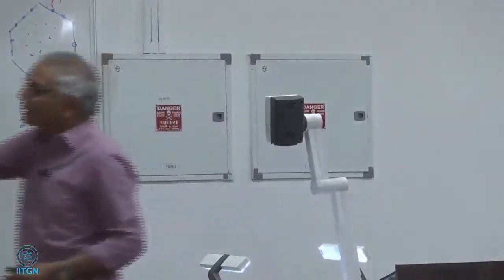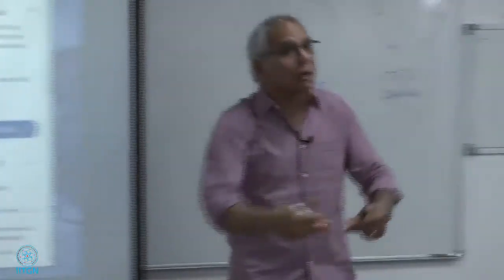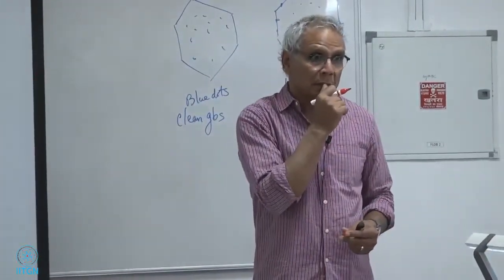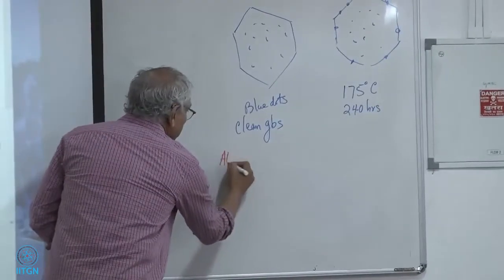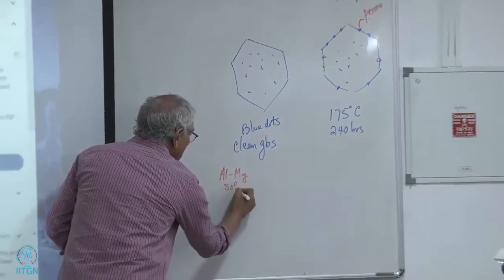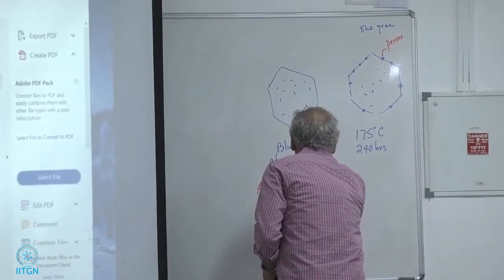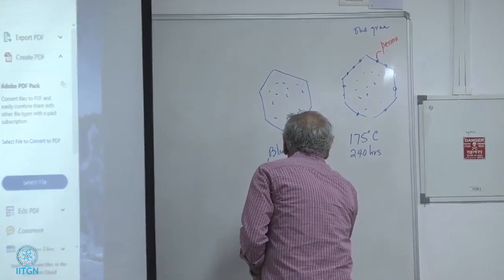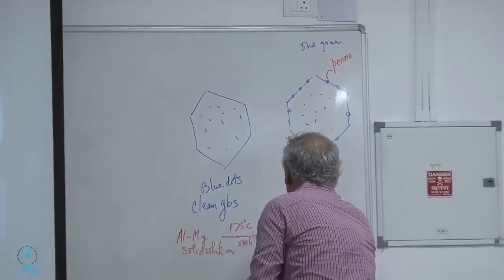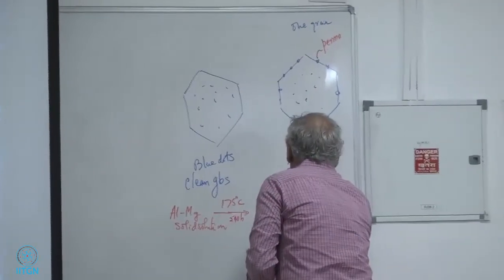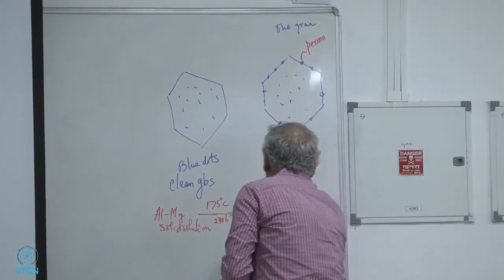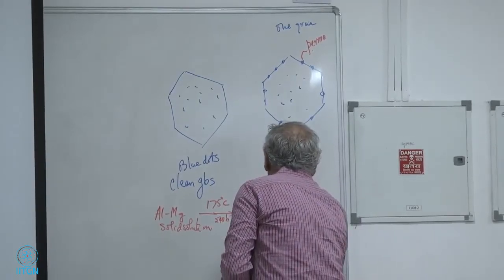Well, I have to be careful when I say the word permanent, because if I put it in the oven at a higher temperature than 175 degrees Celsius, they will dissolve again into the solid solution. So it's like this. So aluminum, magnesium, solid solution. I take this alloy, 175 degrees Celsius, 240 hours. I get the grain boundary Al3Mg2 precipitates at the grain boundaries. That is the chemical reaction that is taking place.